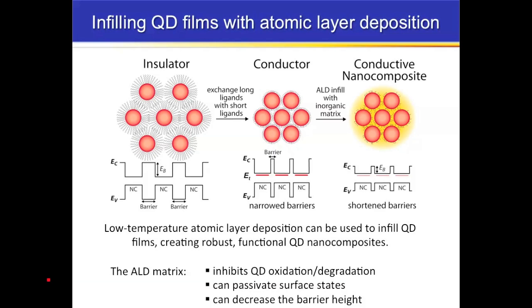And so we decided to solve this problem, and we've been quite successful in using a strategy of low temperature atomic layer deposition to basically completely inhibit the oxidation and the other kinds of degradation that these films suffer. So what we do is we take an insulating film, we use a ligand exchange to make a conductive film, and then we do low temperature atomic layer deposition to infill all the interstitial spaces between the quantum dots with some sort of material like aluminum oxide, Al2O3, another oxide, or perhaps a sulfide.